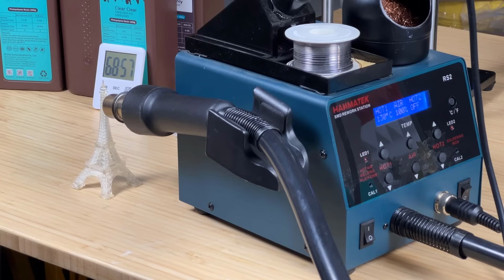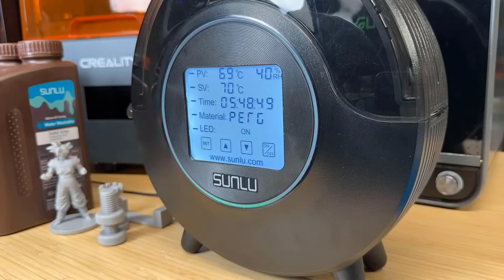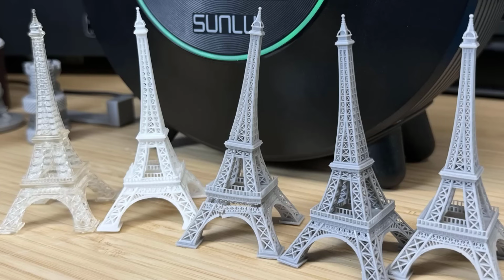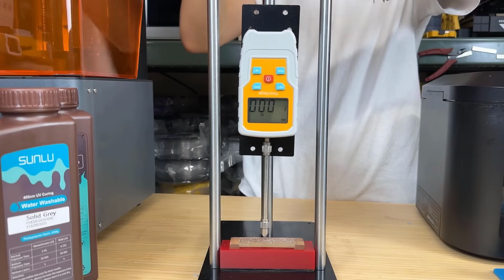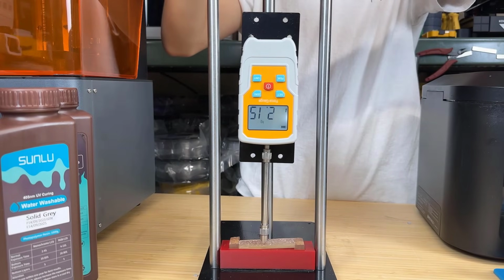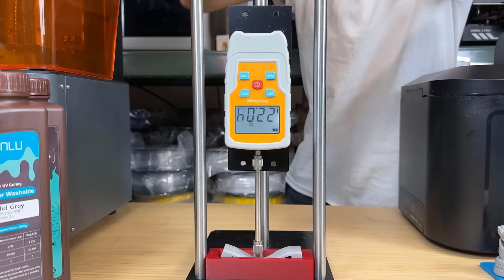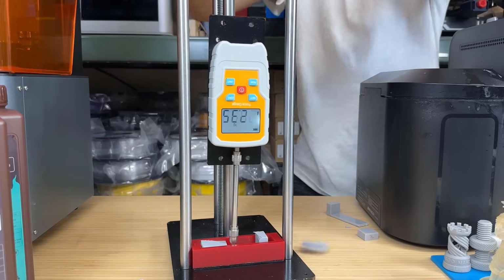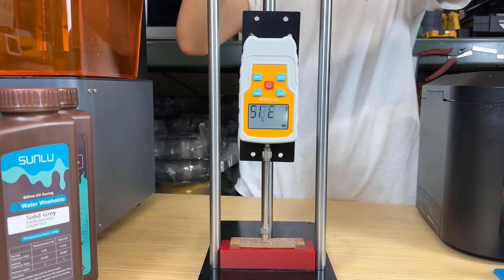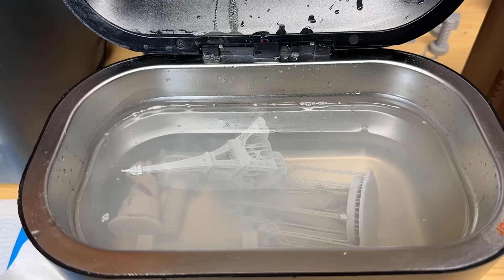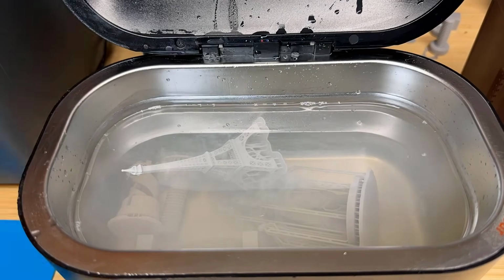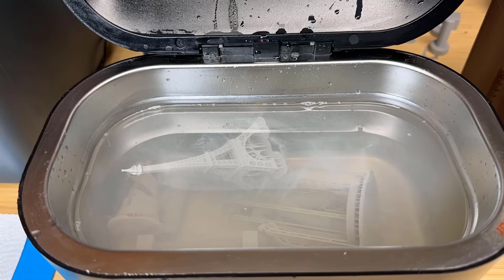The high-temperature resin can withstand temperatures of up to 130 degrees Celsius, whereas the standard resin cracked when I placed it in a filament dryer at 70 degrees Celsius for an hour, although all other resins withstood that same temperature. However, the toughness of the high-temperature resin is the weakest. While the standard resin can resist 22 to 23 kilograms of pressure, this high-temperature resin can only take around 9.5 kilograms.